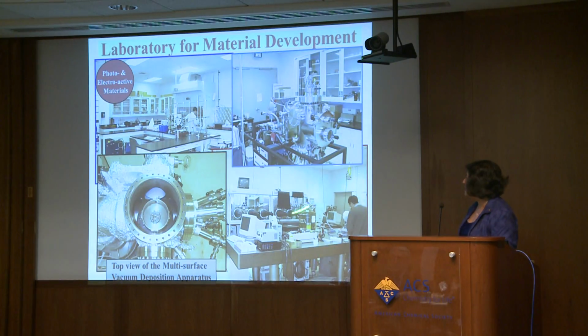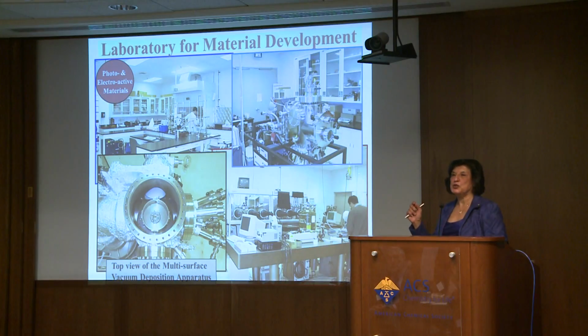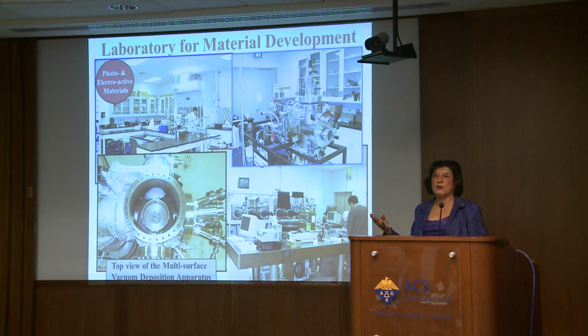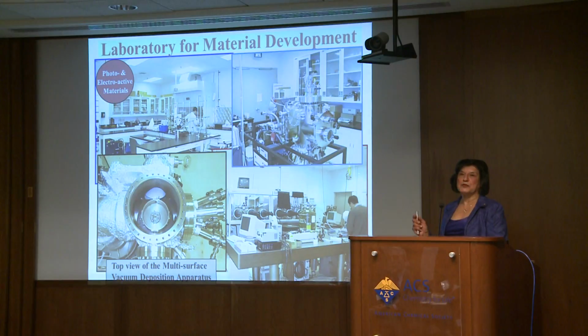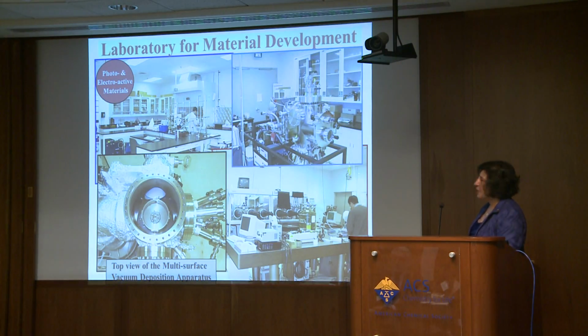So these are some of the facilities that we developed at NRL, a chemistry lab. This is another version of this, the connection with matrix isolation. So in a matrix, you disperse molecules in a rigid inert gas at very low temperature. Here we deposited materials at room temperature, a mixture of a guest-host system, and I'll explain it a little bit later. And in this machine, we can do characterization in situ, or we can take whatever we deposit, the substrates are movable, and do the characterization inside the dry box, which is filled with an inert gas.